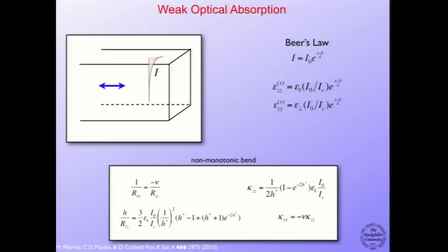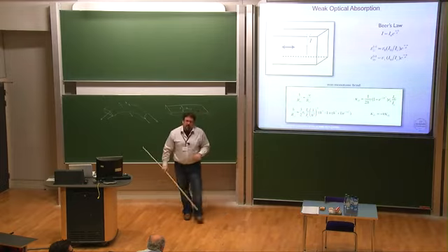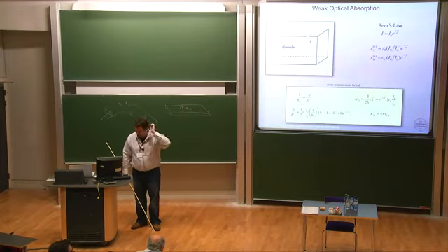So the style of the bending, in a given state, is again the same as the traditional, externally loaded bender. But the interesting thing about this system is that the actual amplitude of the bend that you get is not monotonic as a function of the thickness of the material. The way to understand that is to consider the thickness of the material relative, of course, to the penetration depth, d. And that's what this H star is. I should have written that down. H star is just H over d. That's the scaled thickness of the material.